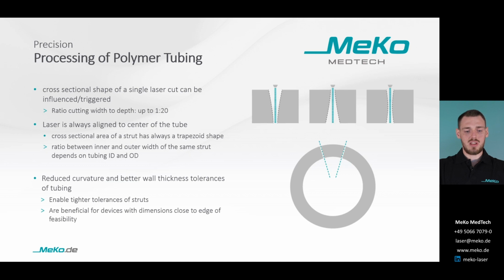If we have a look at processing a polymer tubing, the laser is always aligned to the center of the tube as sketched on the bottom right figure. So the resulting cross-sectional area of the laser cut strut has always a trapezoid shape, and the ratio between inner and outer strut width depends on the tubing geometry. For the best possible result, these parameters must be very well adjusted, which in turn requires high dimensional uniformity and straightness of the tubing.